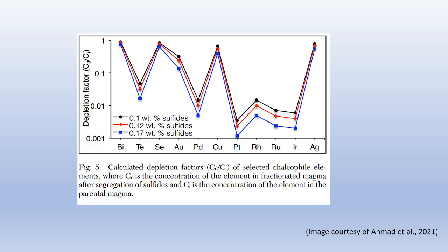And this figure is one of the clearest demonstrations of how powerful the sulfide filter can be in deep arc crust. What you're looking at here are depletion factors, essentially how much of each chalcophile element remains in the magma after a small amount of sulfide melt segregates. The three curves represent slightly different amounts of sulfide segregation: 0.1, 0.12, and 0.17 weight percent. That is less than a fraction of a percent, yet the effect is dramatic.